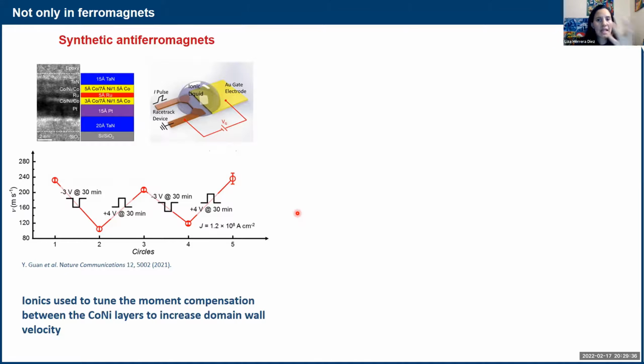And they did this, and they showed they could go to very, very high velocities by spin torque in this type of system. Then they took this idea and said, well, let's keep this synthetic antiferromagnet structure, and let's try to apply an electric field to the top one and do magnetoionics on the top layer, so that we can compensate more or less the magnetic moment in the other layer. By doing that, they got huge changes in the domain wall velocity. Here you can see it's hundreds of meters per second of difference when they set this state to this state, just by a little pulse of electric field.